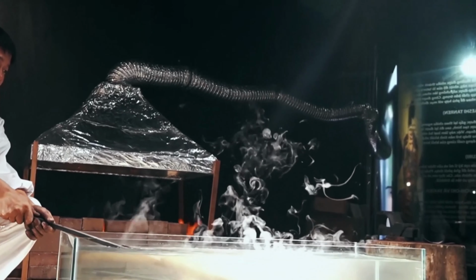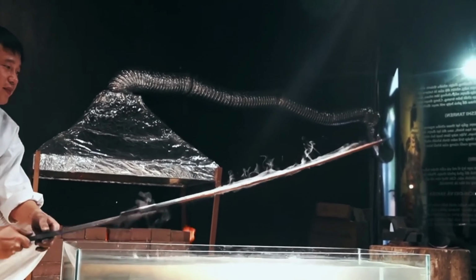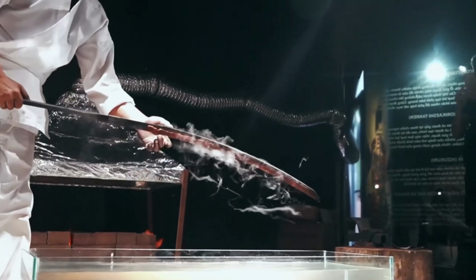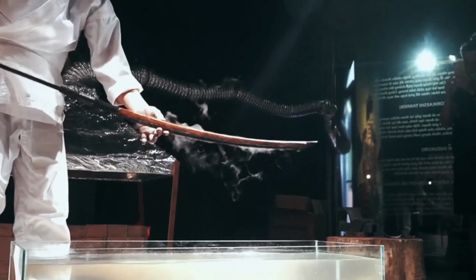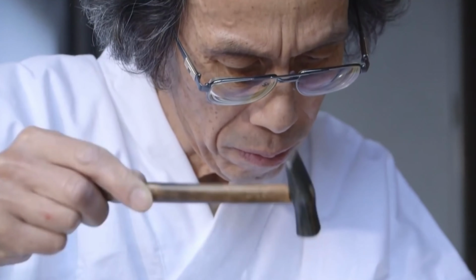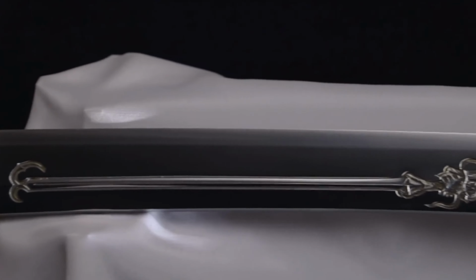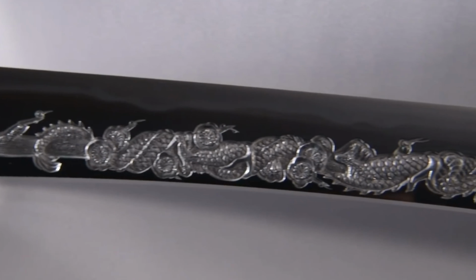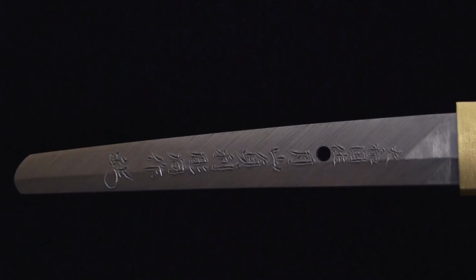The last element, the clay, on the blade makes martensite, hamon, super hard edge. The hamon edge has martensite, very hard, hardened; the body and back has pearlite, ferrite, more flexible, tempered, toughness. Hardness values in VHN for Japanese swords are the following: 650 to 800 VHN for the edge, 400 to 300 VHN for the sides, and 300 to 190 VHN for the core. But please keep in mind that values could change a lot. It is possible that the monosteel swords made in the 16th century in Japan had lower hardness at the edge.